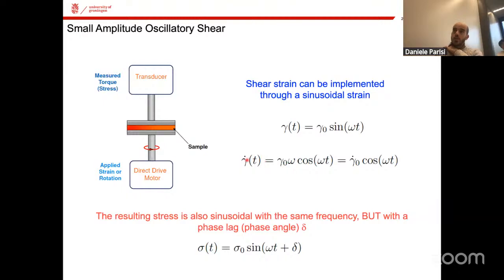So how much strain units we change as a function of time. And that's basically the cosine of this input signal. Okay, so if this represents the input of our rheometer to our sample, we are going to get, via the transducer, a resulting sinusoidal function, which is basically the stress. So we insert the strain via the rheometer, and we get the stress as a response. So you see that now the response has a sort of phase shift, which is this delta.